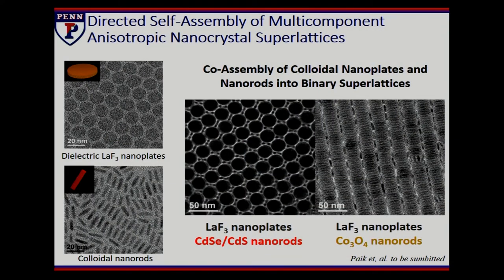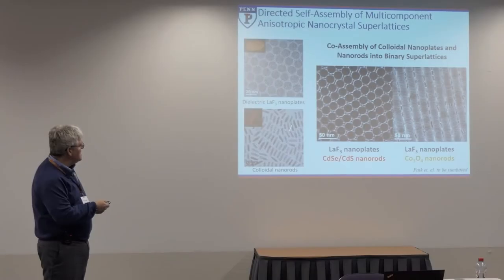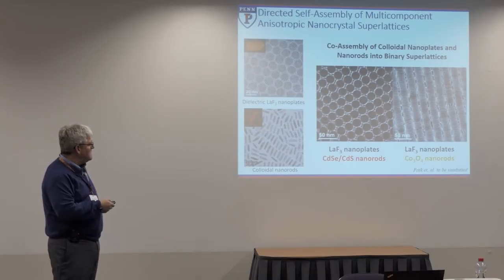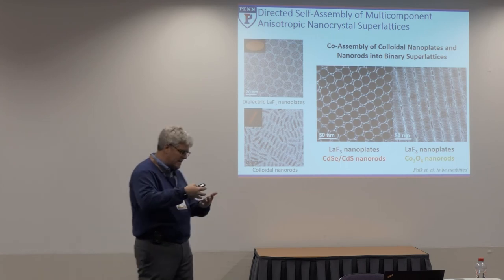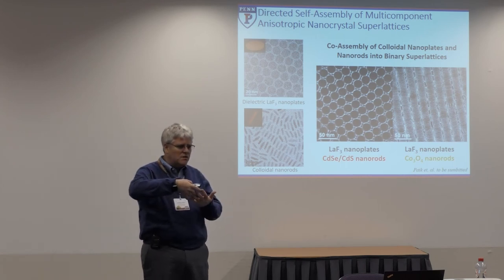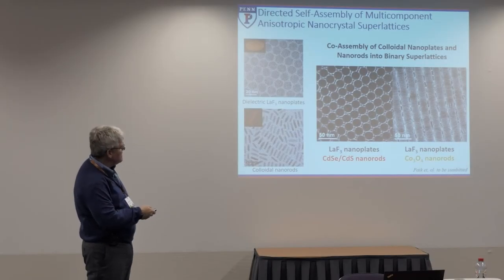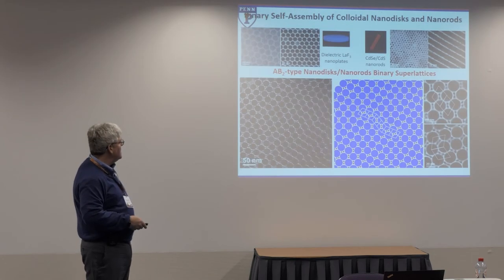Once you have control of the building blocks, then you can start to think about a much wider range of architecture. So in this particular case, it's combinations of rods and disks. And the motivation here is to try to see if you could get systems that were continuous and organized in orthogonal directions. So the disks are packing out of plane, and the rods are standing orthogonal to the base of those disks. Here's a tilted example of the pieces, so the rods are sticking out of plane and the disks are flat and stacking up.